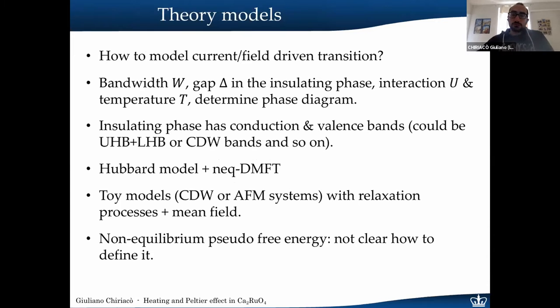So, more on these theoretical models, there is the question of how the current or field applied to the system actually drives the transition. The usual models we consider are systems with a certain bandwidth W and a gap delta, so there is an insulating phase and a metallic phase, and the insulating phase has a certain gap delta. And usually there is also some interaction strength, because these are correlated systems, so there is a competition between on-site interaction between electrons and hopping, the kinetic term. And then there is temperature T and all these parameters that determine the equilibrium phase diagram. These systems usually have this insulating phase with a conduction and valence band, and they can be studied by different techniques.